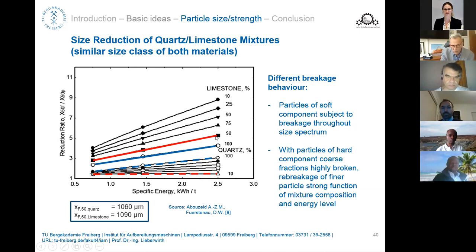So we found this quite interesting, particularly if you are looking at future applications of confined bed comminution for ore grinding and selective grinding in ores. The point here is we have the same sizes. So at least at the beginning, of course, afterwards, the limestone is crushed further, so we end up with finer limestone fractions and with the quartz fractions.